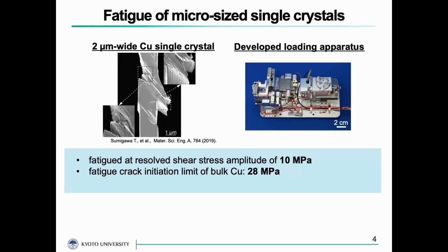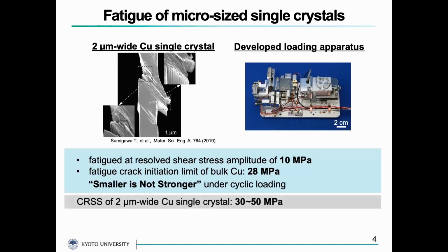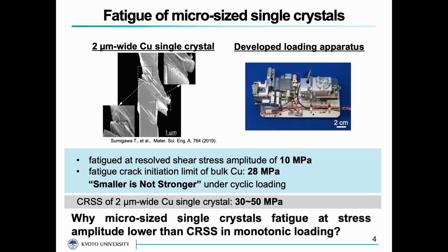So smaller is not stronger under cyclic loading. And moreover, micro-sized copper single crystal fatigues at a stress amplitude lower than CRSS of such size. Because fatigue of metals appears as a result of accumulation of finite plastic deformation, it is questionable why micro-sized single crystal metals fatigue at a stress amplitude clearly lower than CRSS in monotonic loading.